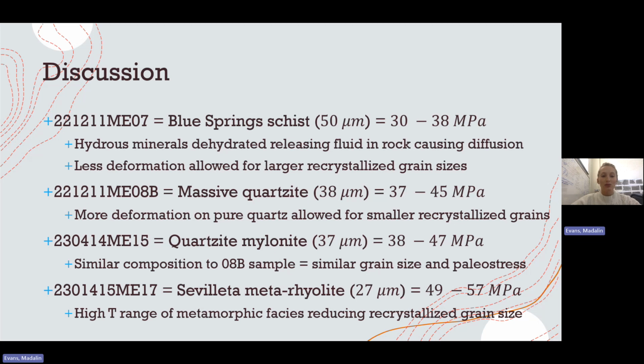One idea is that knowing that the Blue Spring Schist is made up of a protolith of shales and siltstones, which are some hydrous minerals, as this unit experienced some low-grade metamorphism, these minerals were dehydrated, releasing some fluid within the rock, causing diffusion and allowing for these recrystallized grains to continue growing. Another idea is that deformation drives recrystallization, in which the recrystallized grain sizes get smaller as more deformation proceeds. That would mean that this unit experienced less deformation, allowing for the larger recrystallized grain sizes. So keeping that idea in mind, the 08B sample was the massive quartzite unit, and that had a mean recrystallized grain diameter of 38 microns.